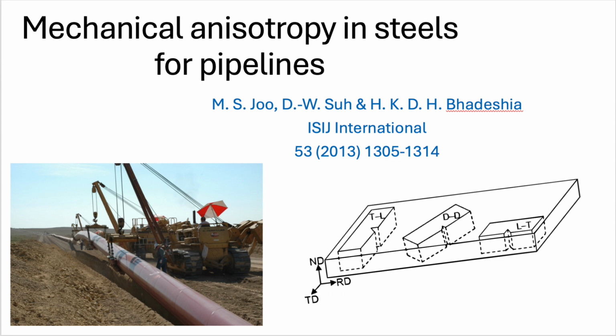Absolutely. Yeah. It correlates directly with the shape, the aspect ratio, of these MnS inclusions. And here's something interesting, almost counterintuitive from the sources. The sulfur paradox. A paradox. Go on. You'd naturally think lower sulfur content is always better for reducing this problem. But one study found a case where a steel with higher sulfur actually showed less anisotropy than a lower sulfur version. Wait, what? Less sulfur made the directionality worse? How does that work?